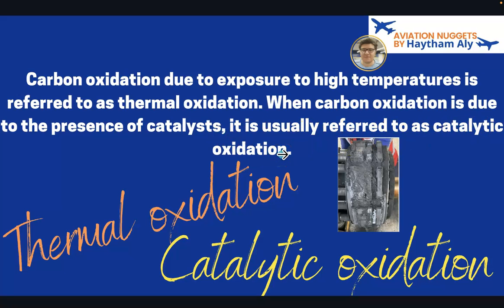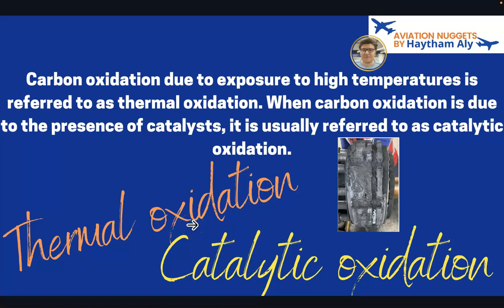So you as a maintenance personnel or as a pilot, how can you identify a thermal oxidation and a catalytic oxidation? As I said before, if the affected disc is a mid disc, it is a thermal oxidation. Vice versa, if the affected disc is the outer disc, it is probably a catalytic oxidation.